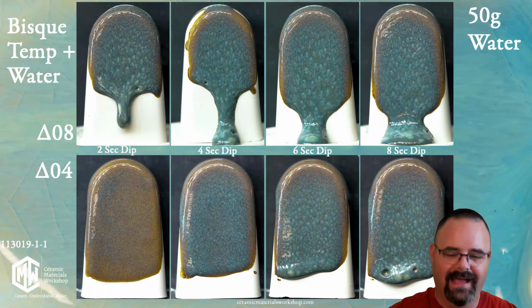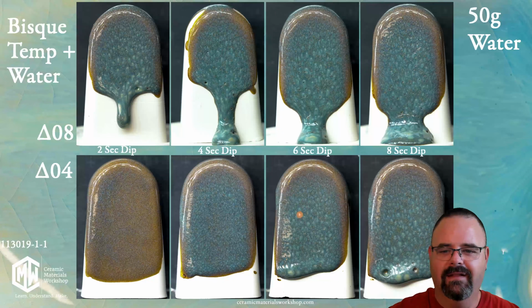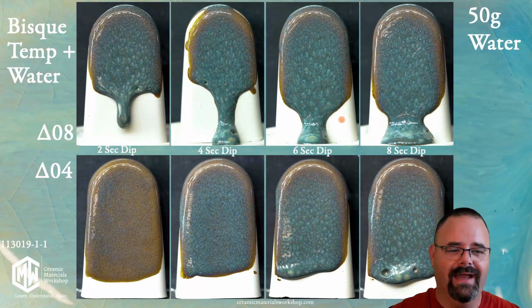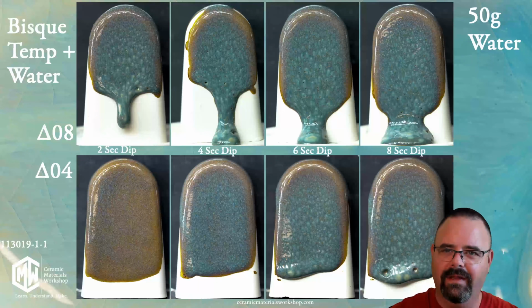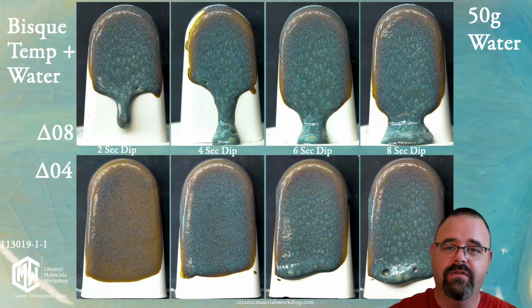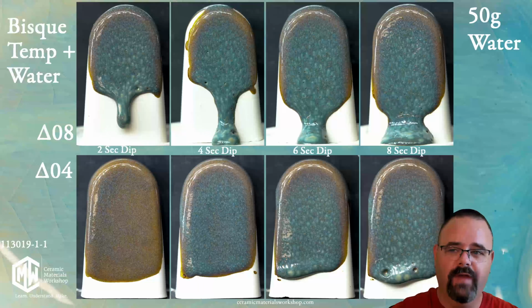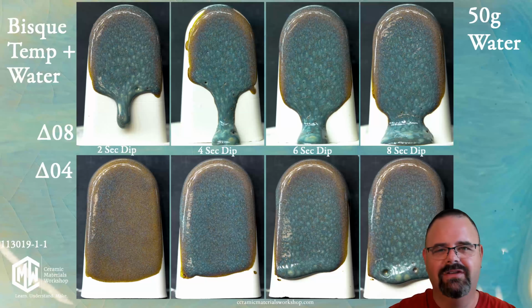Well, we have to go back to capillary suction. You see, at cone 08, my body has higher absorption, which means my clay body absorbs more water, which means it pulls more particles to the surface on application. So as the glaze gets applied for longer and longer periods of time, we are getting a thicker and thicker coat. In fact, this shows a beautiful example of something I consistently teach: glazes really run for 2 reasons. 1, they are too thick, and 2, they are overfired. Now, this is a circumstance where the glaze is too thick, and too thick actually affects the quality of this glaze.